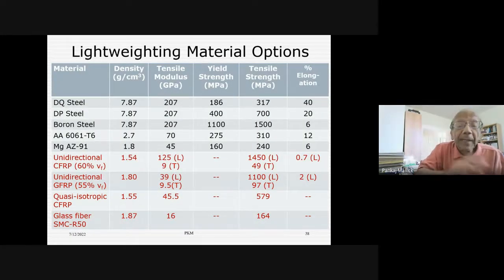So here's the comparison that I quickly wanted to make. DQ steel is the standard low carbon steel. Look at the density, 7.87 grams per centimeter cube, which is the second column on this particular table. The modulus is 207 gigapascal. Yield strength is 186. Tensile strength is 317. Elongation is 40. That's the ductility. Look at the DP steel. DP stands for dual phase steel, which is one of the advanced high strength steels. Look at the yield strength of the material and the tensile strength, much higher than the low carbon steels.